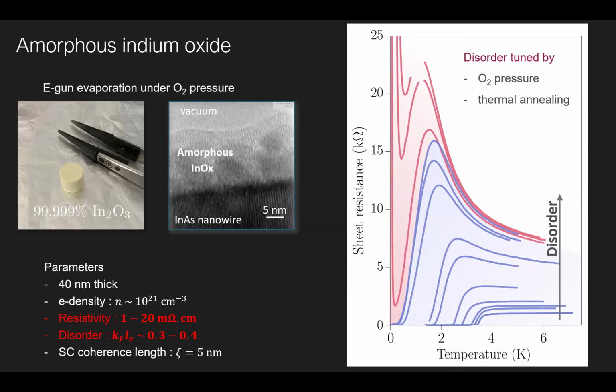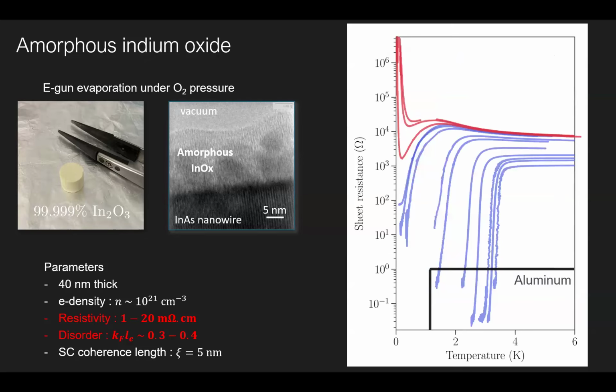For those who are not in the field, I just want to point out that the disorder we are considering here is insane. Resistivity reaches 1 to 20 milliohm centimeter. You have very little superconductor that can exist with such a resistivity. There is actually one example: very underdoped LSCO cuprates reach these values and are still superconducting. If you are still not convinced this is very disordered, I want to show you this curve that I like, in semi-log, exactly the same data. And here I placed, with PowerPoint, the superconducting transition of aluminum. You can see that you have 4 orders of magnitude difference in disorder between our conventional superconductor and these disordered superconductors. All right.